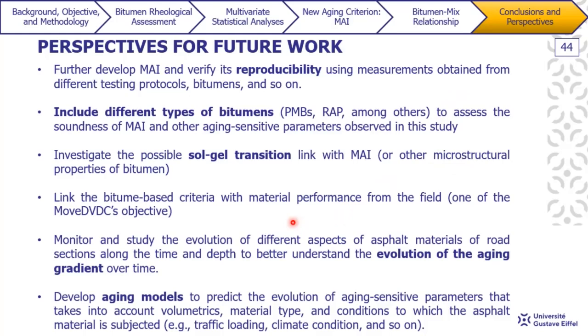Also, in line with the MoveDVDC project, we'll continue the linking between the bitumen-based criteria with material performance from the field, and then monitor and study the evolution of different aspects of asphalt materials of road sections along the time and depth to better understand the evolution of the aging gradient over time. To finally develop aging models to predict the evolution of aging-sensitive parameters that take into account volumetrics, material types, and conditions to which our asphalt materials may be subjected during pavement service life, such as traffic loading, climate conditions, and so on.